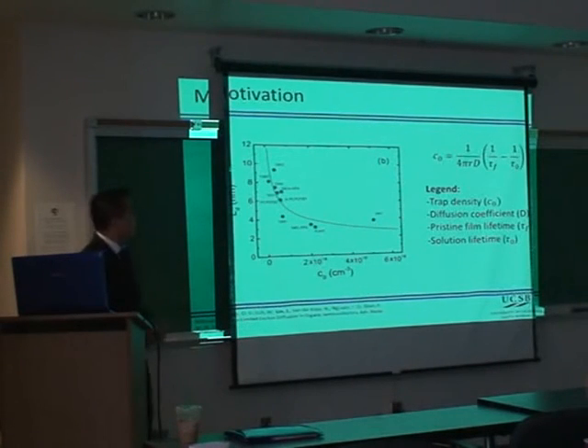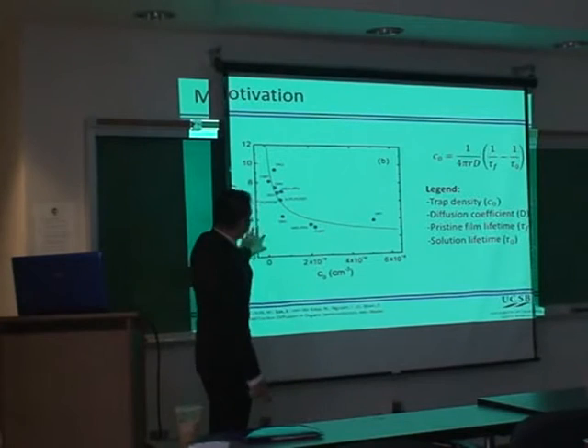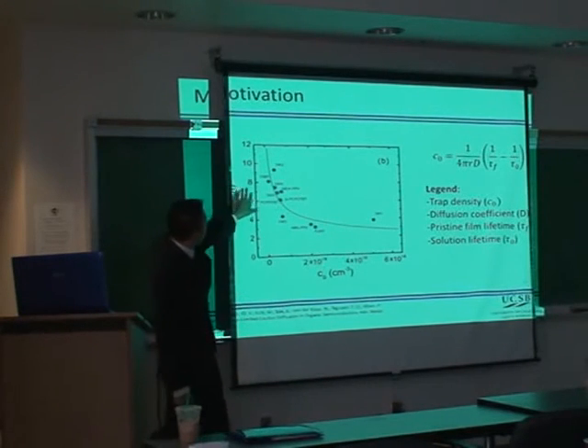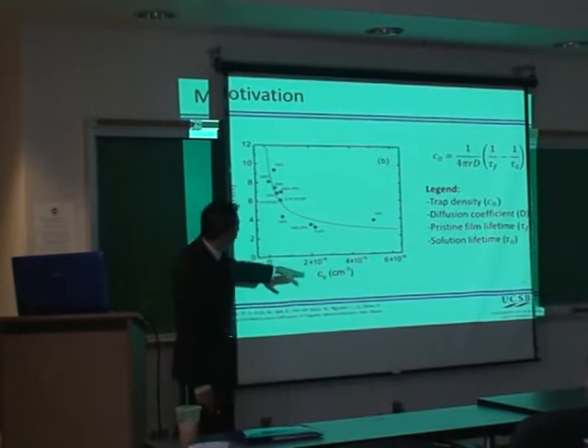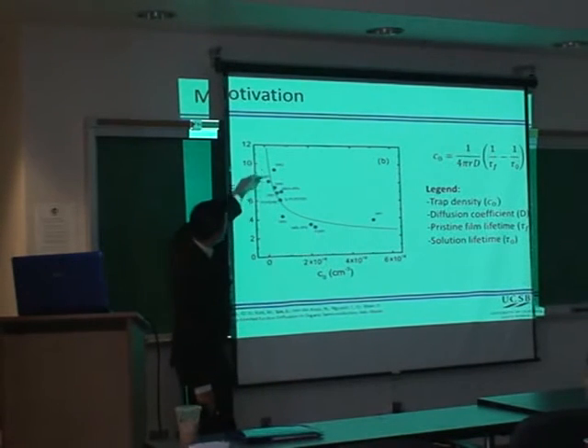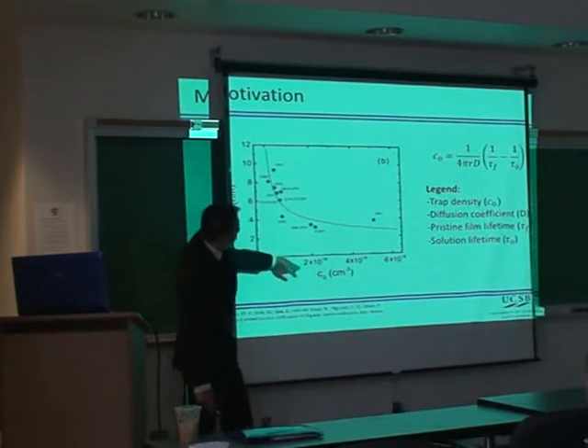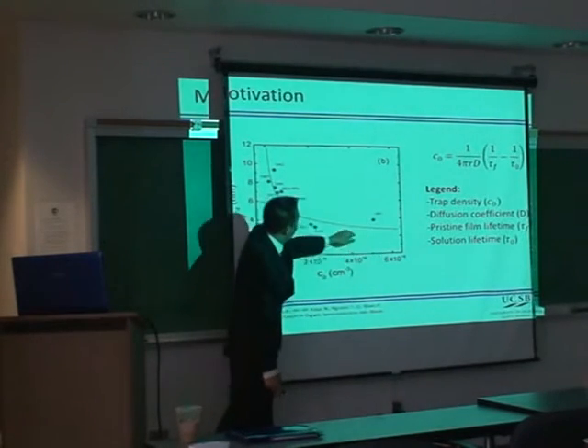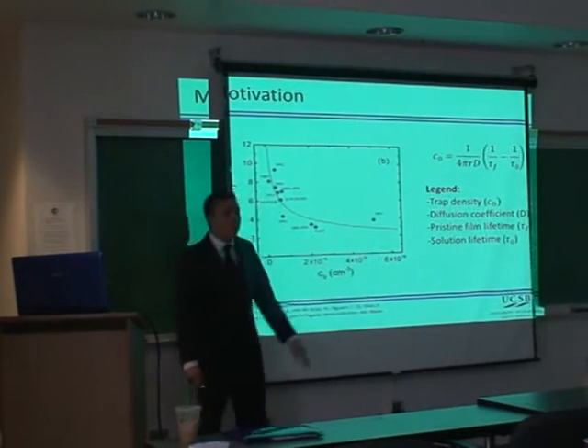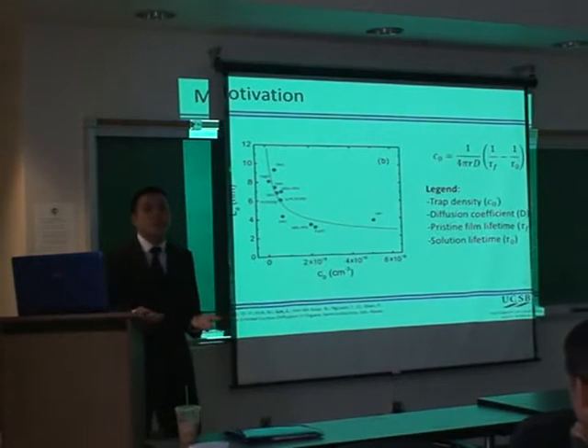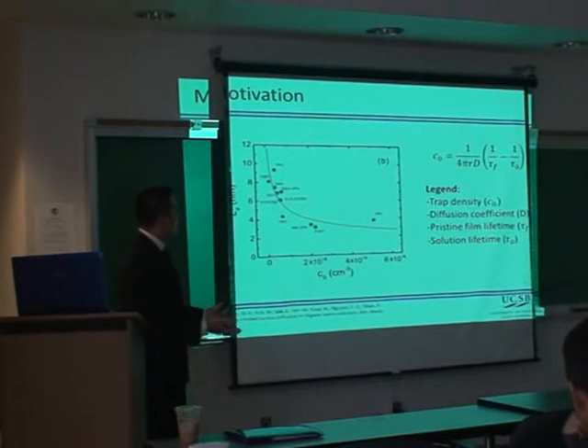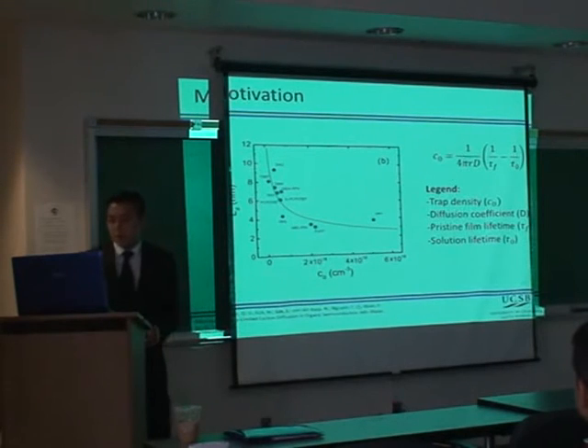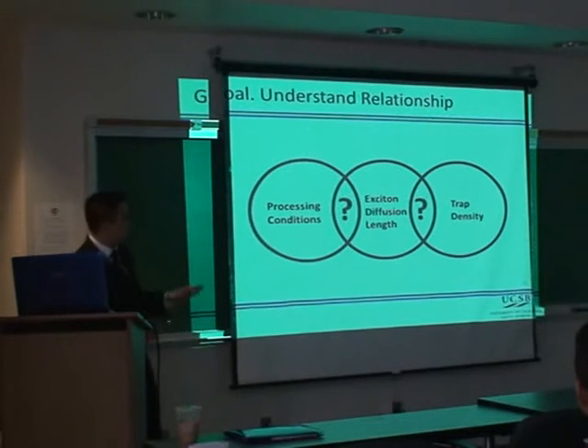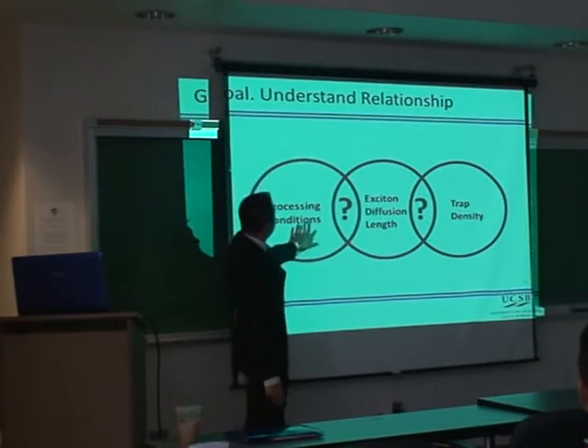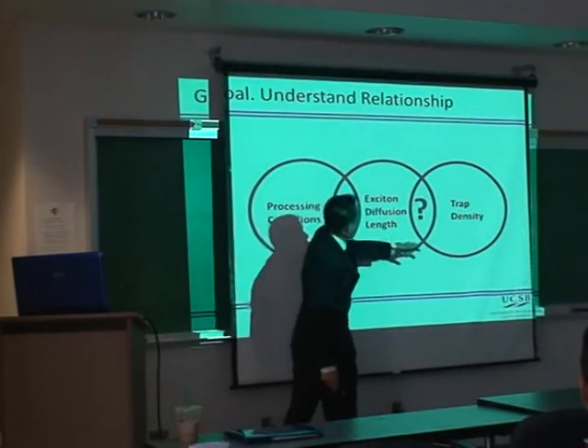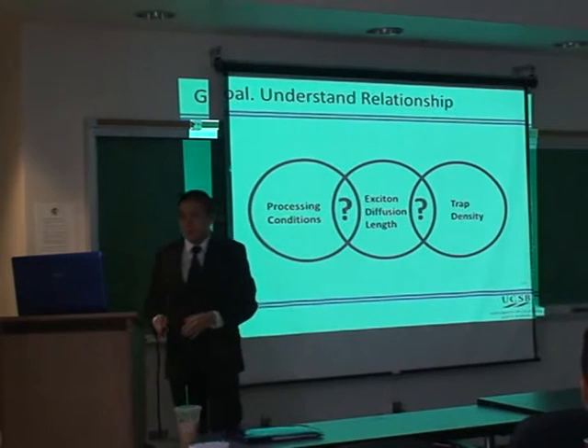Another motivation for this study was that another publication by a colleague showed that when you compare the exciton diffusion rate for different materials and a calculated trap density, you find this trend where when you have a larger concentration of traps, you have a shorter exciton diffusion rate. So what I wanted to see is, does processing affect the number of traps, and how does it connect with the exciton diffusion rate? So big picture wise, I want to find out the relationship between processing, exciton diffusion rate, and also trap density with the exciton diffusion rate.